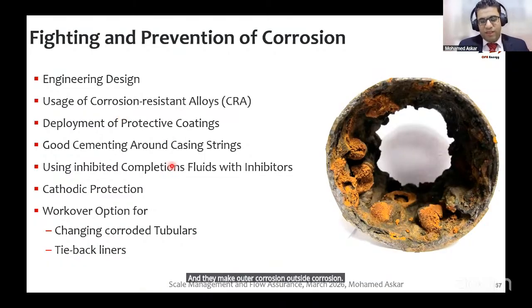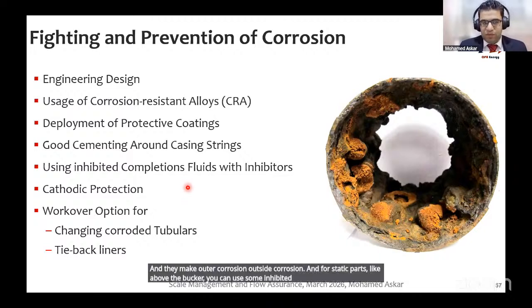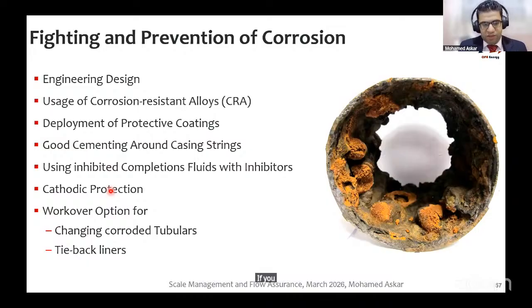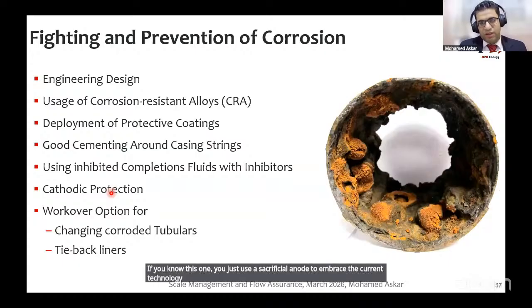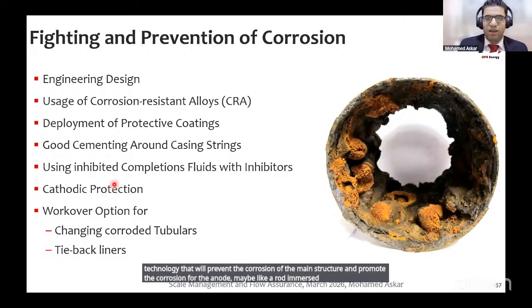And for static parts like above the packer, you can use inhibited completion fluids with inhibitors to prevent the corrosion. And for big facilities like pipelines, offshore platforms, and tanks, you should use cathodic protection. You use a sacrificial anode or impressed current technology to prevent corrosion of the main structure and promote corrosion of the anode, maybe like a rod immersed in the ground, and after some time you can change it with a new one.